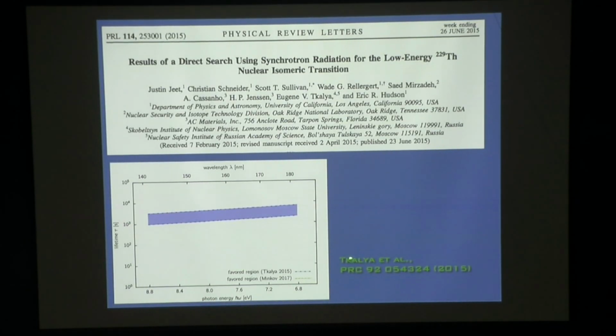This is something we did with Eugene V. Tkalya in Moscow. And so we didn't see anything, and we could produce an exclusion. So the red region is the area that we could exclude at roughly a 90% confidence interval. So we took a big bite out of this parameter space.